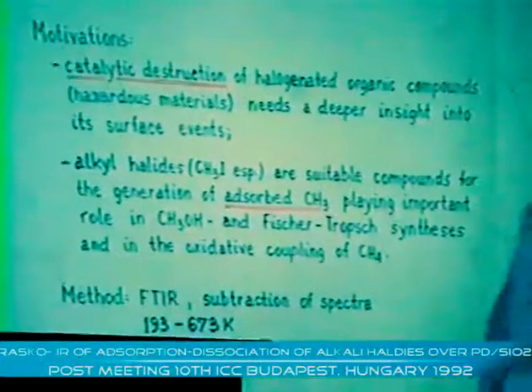The second thing, these alkyl halides, particularly methyl iodide, would be suitable compounds for the generation of adsorbed methyl, which plays an important role in many syntheses like methanol synthesis, Fischer-Tropsch synthesis, and even in the oxidative methane coupling. There was a certain personal motivation which was killed by Helmut Metzinger in his lecture. So I have to modify my original sentence. Although there are many papers dealing with adsorbed methyl on single crystals, till the lecture of Professor Metzinger, nobody saw adsorbed methyl under real catalytic circumstances. His detection in catalytic circumstances, that means at elevated pressure and on a supported oxide, should have been a personal challenge for us.